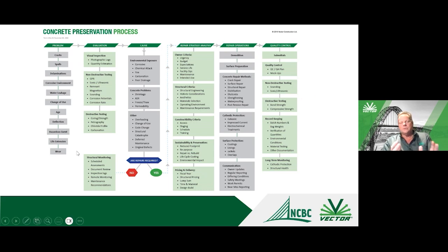So basically the point here is that rather than just jumping in and doing the repair or a patch, if we're really going to look at the durability of structures, we need to look at it more holistically and really fundamentally understand: is this crack that you see visually caused by corrosion? Is it caused by structural issues? Is it caused by ASR? All those types of things may lead you down a different path on how you might want to fix a structure. So having an understanding of the cause of the damage through an evaluation, and determining not only the cause but the magnitude, and then you develop your repair strategy based on the owner's needs and budgets, all the way through quality control in the field. And once again, I think it's just a nice little guideline. It's available at WeSaveStructures.info.